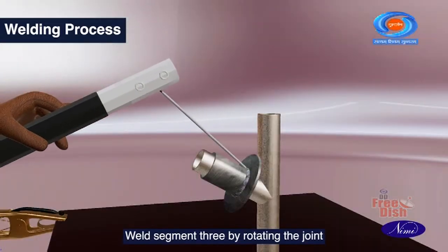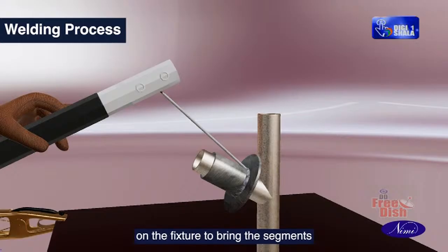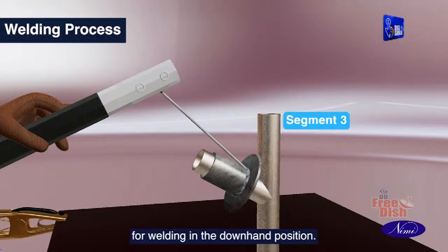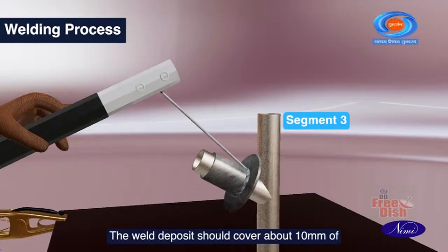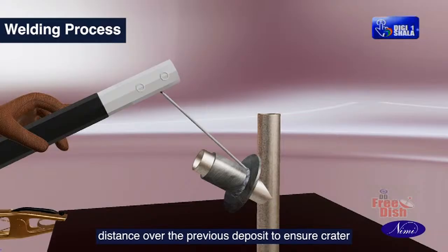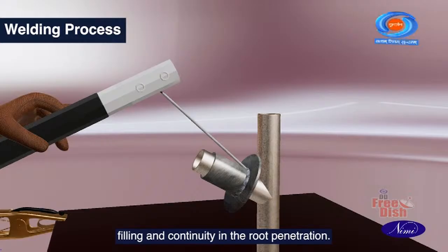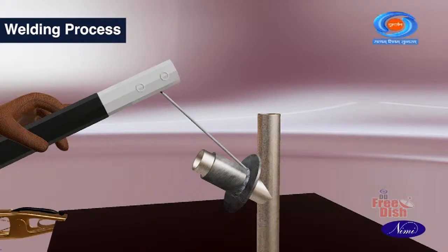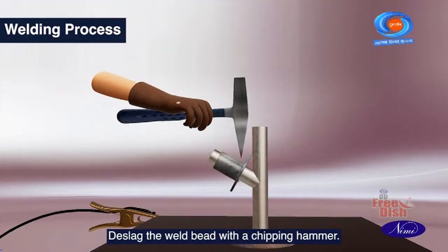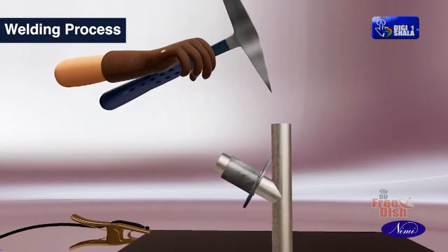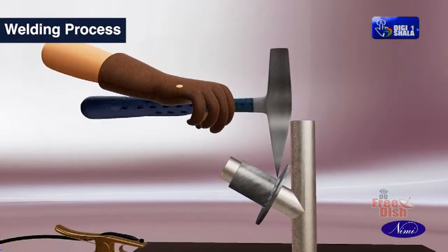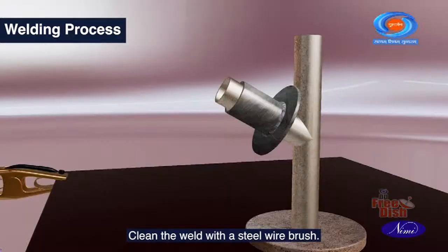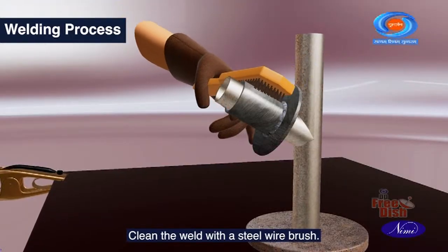Weld segment 3 by rotating the joint on the fixture to bring the segments for welding in the downhand position. The weld deposit should cover about 10 mm of distance over the previous deposit to ensure crater filling and continuity in the root penetration. Deslag the weld bead with a chipping hammer. Clean the weld with a steel wire brush.